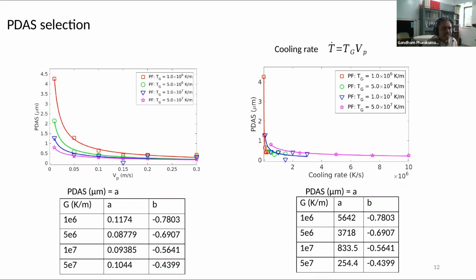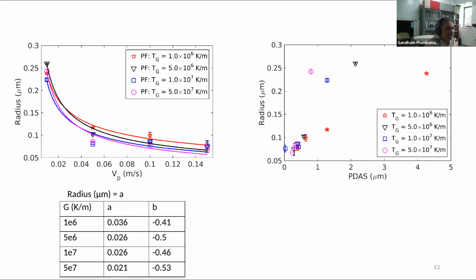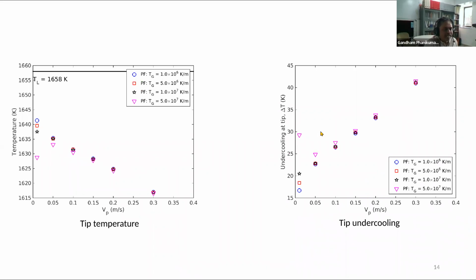So the primary dendrite arm spacing, for example, if you look at the red square versus stars, red square shows you that at a lower gradient you are actually lower here, and at higher gradient you are up here. So that means that for a given cooling rate, you can actually have a primary dendrite arm spacing decreasing if you have got a higher gradient, or if you keep the horizontally, you can see that a higher cooling rate would actually be corresponding to a higher gradient for the same microstructure. Okay, so we will be able to understand the microstructure at every aspect of it, which is experimentally not possible.